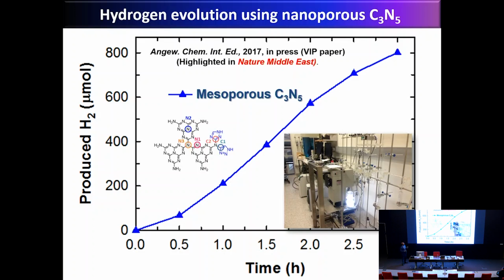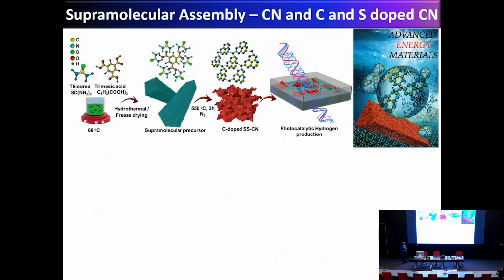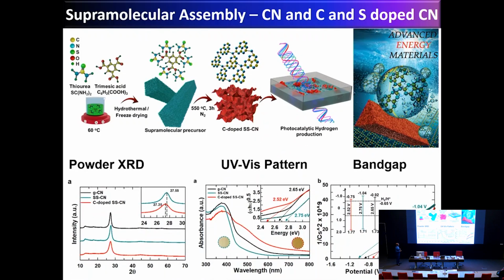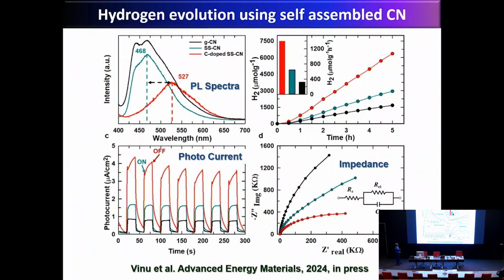But what would happen if you change the surface composition of the material with a different heteroatom? We use a supramolecular assembly approach using thiourea and trimesic acid, and we try to add sulfur and carbon into the carbon nitride material with the C₃N₅ stoichiometry. This was just published in Advanced Energy Materials. Interestingly, the conductivity of the material increases when we dope the carbon and the sulfur, and also that changes the band structure of the material quite significantly.